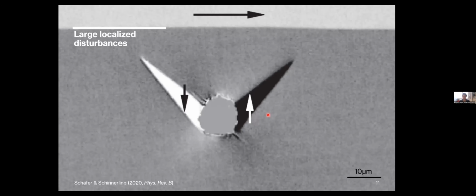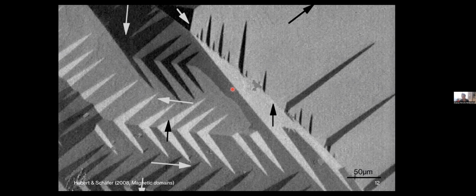And what I mean by that is, if you look through several micrographs of soft magnets, you often see defects in them. Here's an example of a pore defect in a soft magnetic alloy. When you have a pore defect, this could be a non-magnetic inclusion. What happens is the material, to reduce its demagnetization field, forms these spike-like microstructures, or needle-like domains, you see in many of them. And this microstructure is not specific to this alloy, or to just this defect. It's in fact quite ubiquitously found in several of these soft magnets.